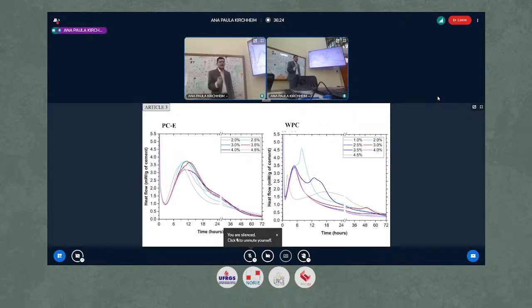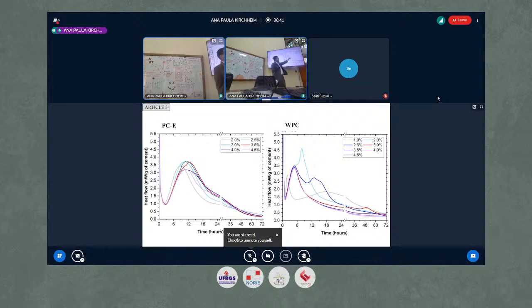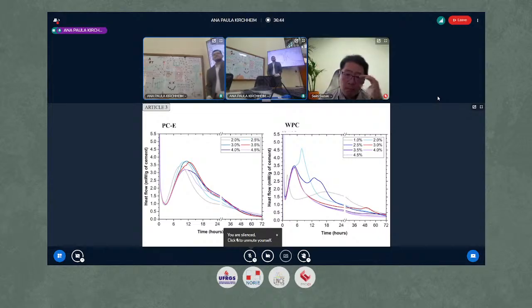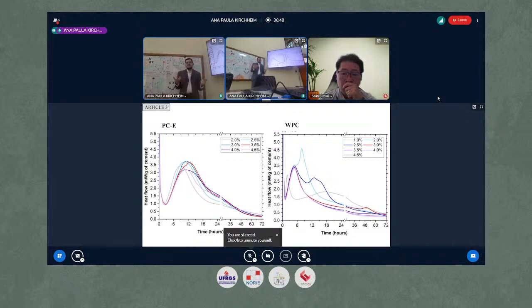And here I compare PCE and white Portland cement clinker. And this was very interesting. We were lucky because PCE has the same content of C3A as the white Portland clinker. So why does the white clinker have the higher peak? You could say, oh, perhaps the C3A content, but PCE has the same content.